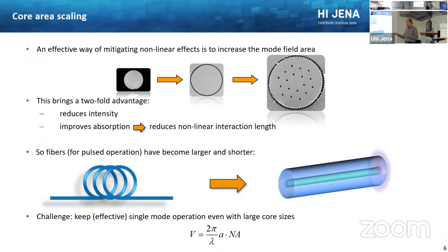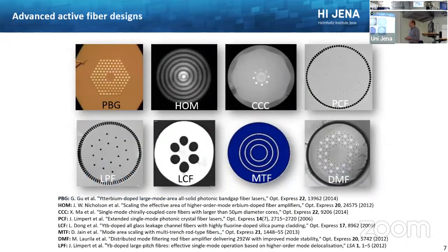So the only choice you have is to reduce the factor on the right side. The wavelength is fixed, you cannot do anything there. But then the numerical aperture you can reduce by making the step index step from your core to your cladding smaller. But this is also possible only up to a certain degree. So you are stuck with fibers of, let's say, 15 micrometer diameter that work in the single mode regime that you want to have. And now to overcome this, a lot of groups around the world have worked on what we call microstructured fibers.